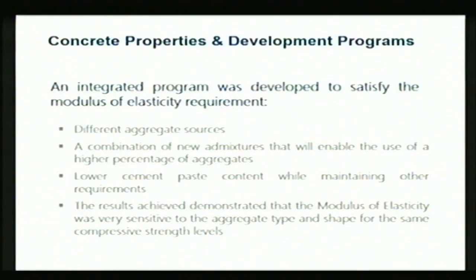And we told the engineer, we changed the aggregates, and we found out that the aggregate shape, the quality of the aggregate, the nature of the aggregate, the geology of the aggregate was so important to get the MOE. And we convinced the engineer that the strength kept increasing, but the MOE was not increasing. So this relationship between MOE and strength, which was proportional, did not work. So when we changed the aggregate, things became better.